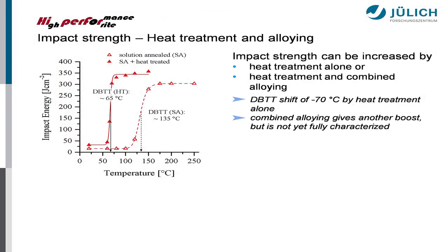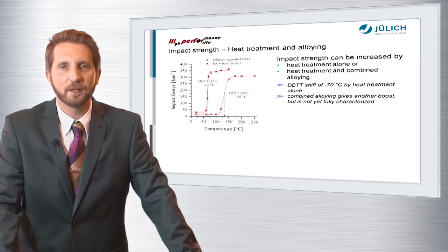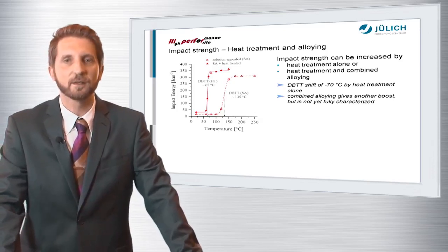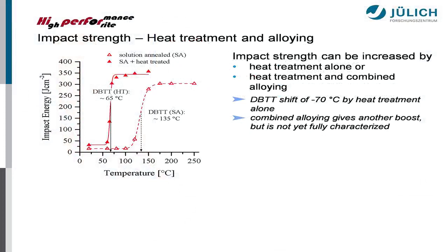But we were able to prove that by simple heat treatment, a ductile to brittle transition temperature shift of approximately minus 70 degrees C can be achieved. So in a solution annealed and heat-treated state, the ductile to brittle transition temperature is approximately at 65 degrees C, and we already found out that with combined alloying, we can further decrease this. We're able to increase the lower shelf energy, and we're very positive that we are able to stick to the European regulations. So for sure, this is another topic which is still subject to further optimization, and right now we're about to implement this heat treatment into our lab scale production.